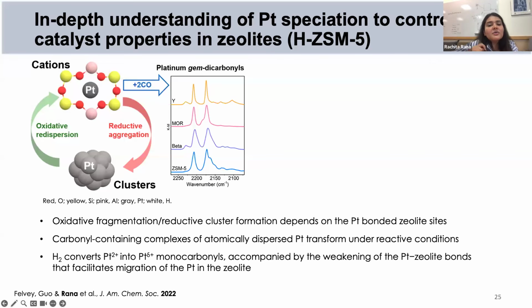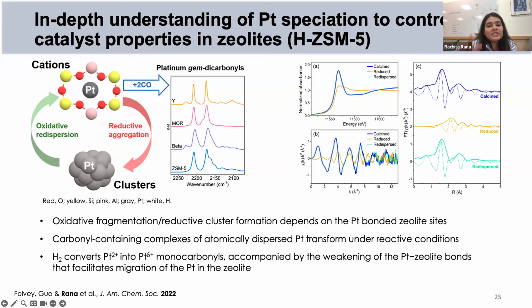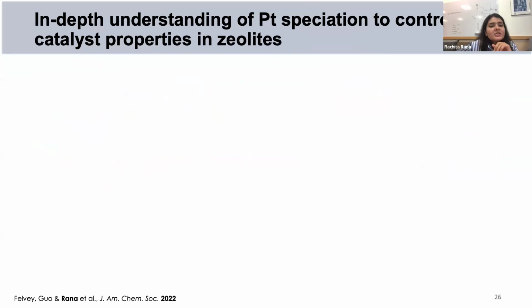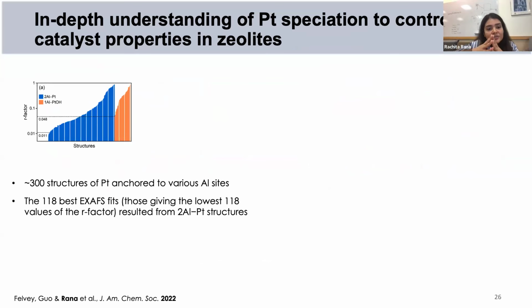And so then the idea was, okay, we're doing this. We went to the beamline, we collected the data, and we knew that, if you look at the curves on the extreme right, figure C, the calcined material looked very similar to the redispersed material, and the reduced material signified metallic platinum. Well, the question was, how do we understand where this platinum is bonded in the zeolite? And so for that, we started using QuantEXAFS.